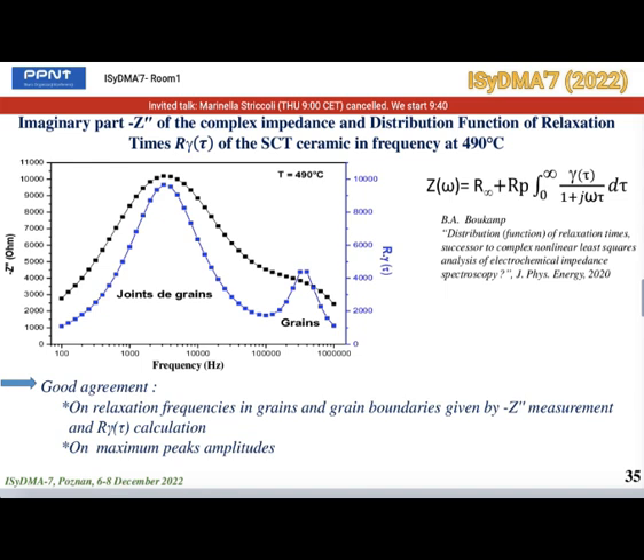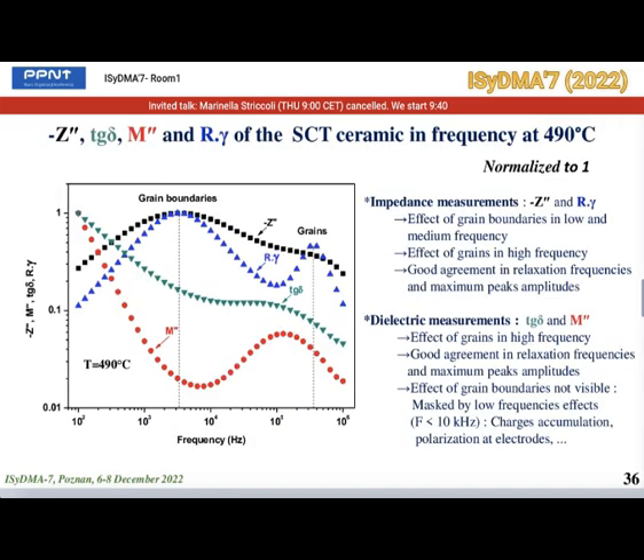The distribution function is derived from the impedance through solving this Fredholm integral of the second kind. By comparing frequency evolutions of the imaginary part of the complex impedance and of the R gamma, we show a good agreement on relaxation frequencies in grains and grain boundaries, given by minus Z second measurement and R gamma calculations, and also on maximum peak amplitudes. Finally, we present here